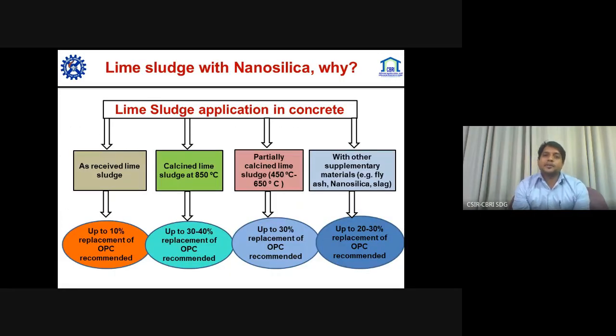But lime sludge with nanosilica, why is it required? When we use as-received lime sludge, according to the literature, we can use only up to 10% replacement of OPC. When we calcine the lime sludge at 850 degrees C, 30 to 40% replacement of OPC is possible. But the calcination is again energy intensive.